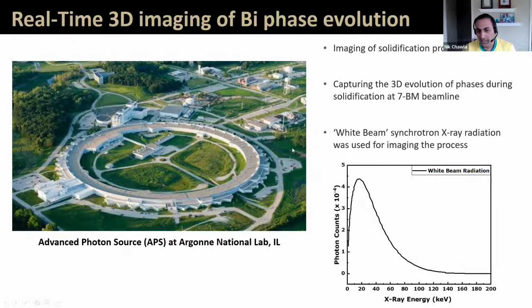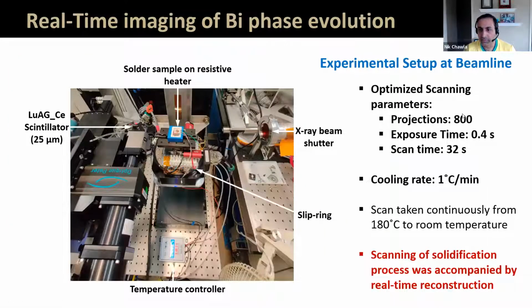Now, the problem with the white beam is that it has a distribution in X-ray energies, okay? And so we want to maximize the range of X-ray energies that will give us the best contrast between tin and bismuth. Okay, so there were several parameters that had to be optimized because, again, we want to get the best image quality, but we also want to scan as quickly as possible. So we started off with 800 projections and 0.4 second exposure time. So a typical scan would take about 32 seconds. That's a little bit faster than the cooling rate here, which is 1 degree C per minute. So we're getting about 2 scans for every single degree change in solidification. Okay, so that's actually a good compromise.